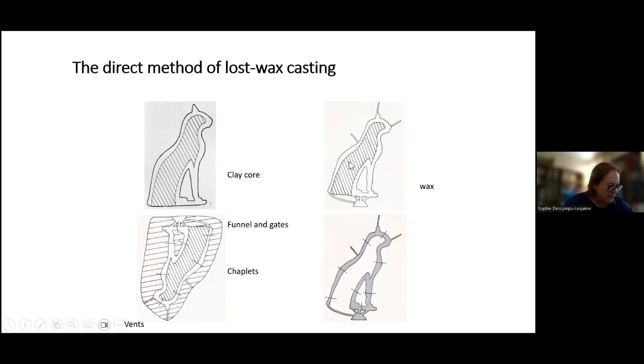gases. A new step was to place pins, you can see pins here, for instance, through the wax to lock them into the core. These pins, usually made of iron, but sometimes of bronze, were called chaplets. They were rectangular in section. The heads were left exposed, so when the casting mold, here is the casting mold, investment was built around the hole, they would hold the core in position after the melting out of the wax.